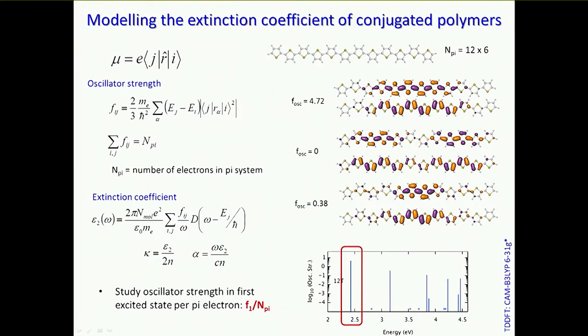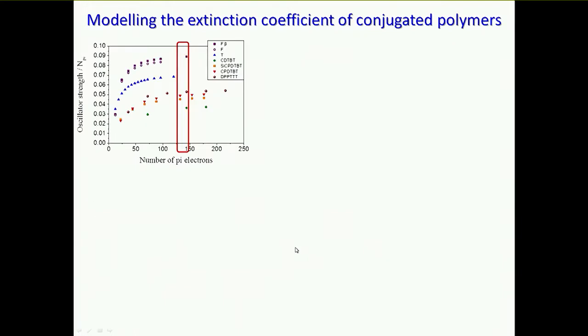So we thought, okay, it must be the case that our DPP TTT has an exceptionally high oscillator strength for its first transition. Let's compare it with the other materials that we know about. So we did that. And first of all, we look at the oscillator strength. In order to normalize things and compare one polymer with another, we look at the oscillator strength per pi electron as a function of the chain length. So we could compare the materials with one another. And the slightly frustrating thing was that our DPP TTT polymer is more or less nowhere. It's not by any means the one with the strongest oscillator strength.